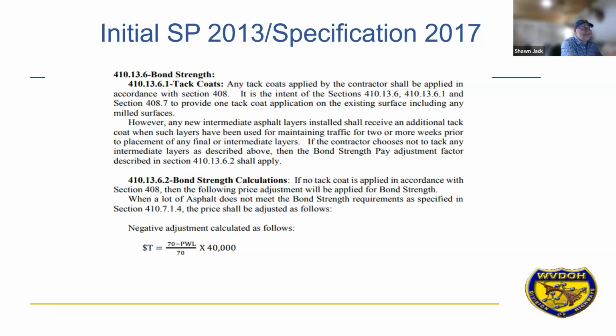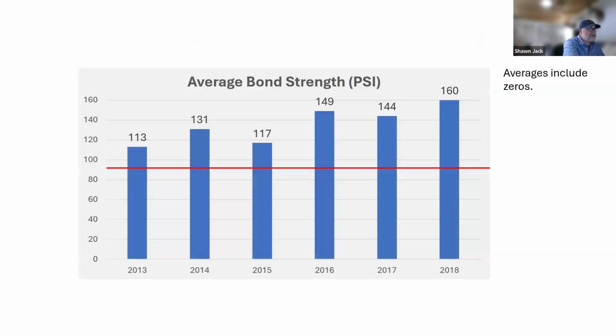The negative adjustment did apply to any failures if by chance you did not use a tack coat, and a few contractors tried us on that. But you can see here in this bar graph how our average bond strength improved over time. So this 2013 to 2018 time frame is under the original special provision, and once the specification went live, but the language in the specification hadn't yet changed. So we are only penalizing if we don't use a tack coat. But you can see that we still saw improvements over time, and all of these averages also include zeros. So, pretty good results.